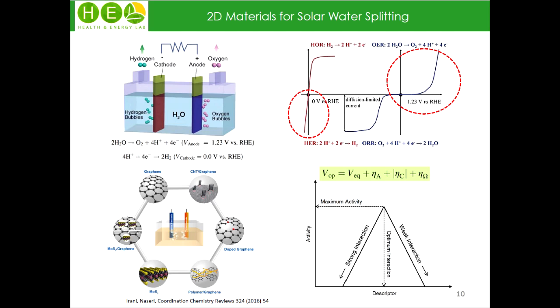In terms of thermodynamics, such water splitting reaction costs 1.2 volts, but considering the kinetics issue, it costs more than this value, nearly 2 volts. Our research should be directed to find a low-cost, stable, and efficient electrocatalyst that could reduce such overpotentials.